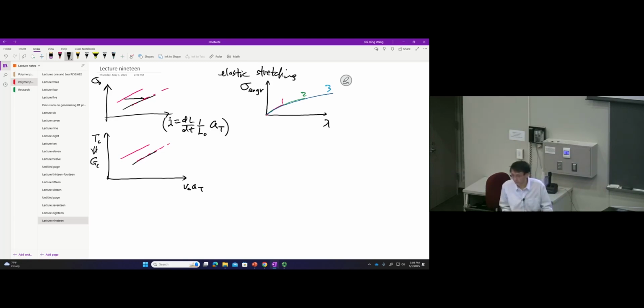That's what this is. But the fact these stress-strain curves overlap means there's no rate response. Do you understand? That means it's purely elastic. Yeah, because you don't need to be in a hurry. Meaning, no matter what temperature and what rate you are performing your experiment, you hit the same stress.